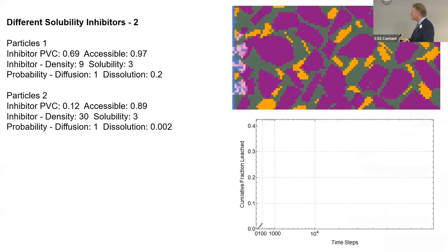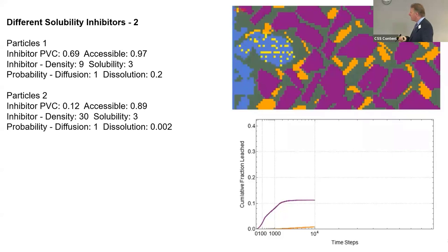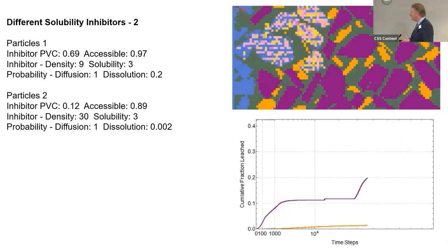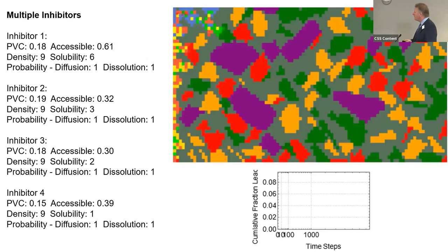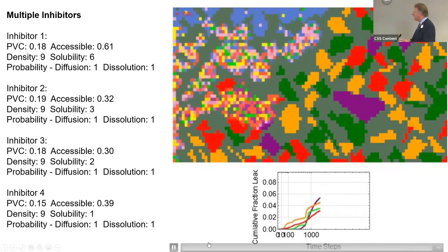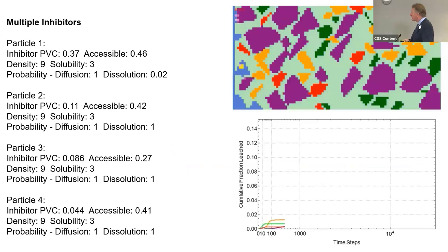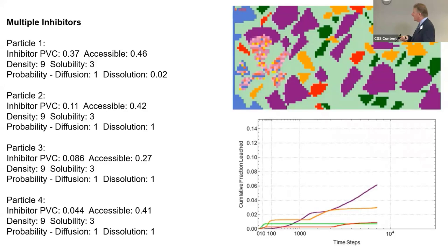Another example of a similar system, again showing the idea of repeating. These are very high levels of loading and high accessibilities. Once again you see very rapid release of the purple particles, slowed down by the orange particles, and then a small amount from smaller particles. You can make systems considerably more complicated — here's a system with four inhibitors in it, and as we actually see in some real coatings where multiple inhibitors are used, you get different levels of release. You can track each of these individually, which is a luxury that's more difficult to do experimentally. By varying the solubilities of these materials, it changes the way in which they behave.